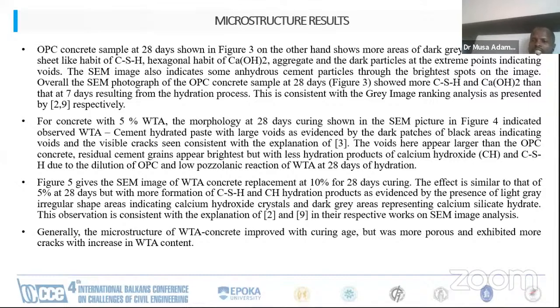The voids here appear larger than in the OPC concrete. Residual cement grain appears brightest, but with less hydration product of calcium hydroxide and CSH due to dilution of OPC with low pozzolanic action of WTA at 28 days.